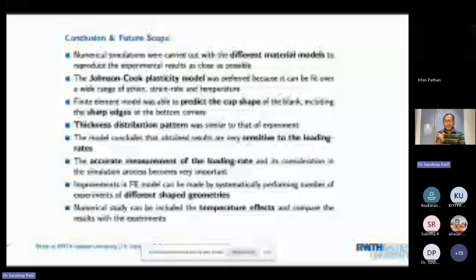Then we found that the simulations are sensitive to the loading rate. You can see nicely smooth results from the low loading rate, a triangular loading, and when you go to reality, it is an extremely fluctuating load. Then again, we can see that accurate measurement of the loading rate is very important in order to have exactly similar